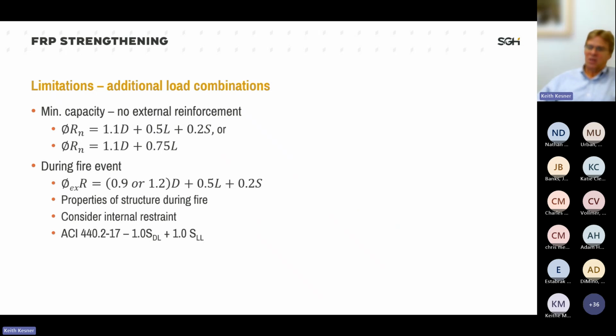And what this minimum capacity also does is provide a backdoor limitation on how much FRP can be added to a structure. What does that mean? When we're thinking about reinforcing something, we're trying to take it up to 1.6 live load. And our minimum is 0.5 live load. The maximum that we're adding in terms of strengthening is about 1.1 times the live load. So that provides a limit as to how much FRP. Why is that important? Because when you put on too much FRP, it just doesn't work. You can't get the strain into it. So this is another way of limiting how much additional reinforcement can be added to a structure, and this further prevents brittle failures of reinforced concrete structures.